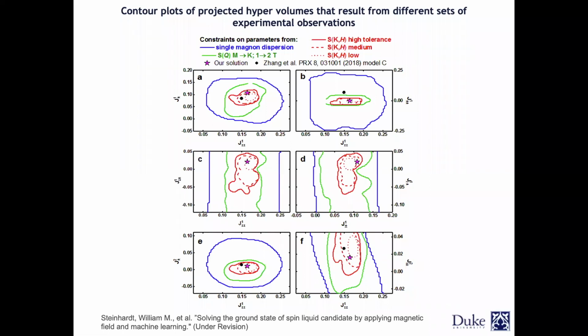at the applied so much field that all the spins have nowhere to go but to align along the field. In that case, if we start to give them some energy, they will produce these quasi-particles called magnons, and those magnons will have a dispersion, and then they can say, okay, so along this dispersion. That data was already published, but only for the phase where the magnetic field was very high, not these intermediate fields from 0 to 5 Tesla.